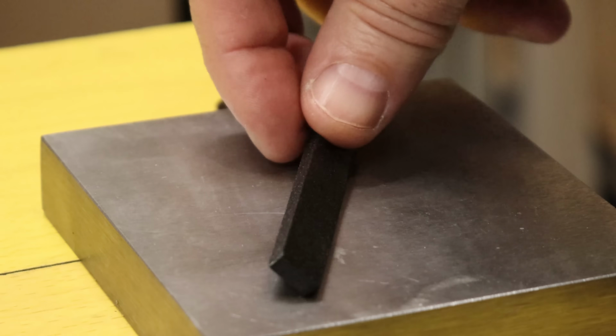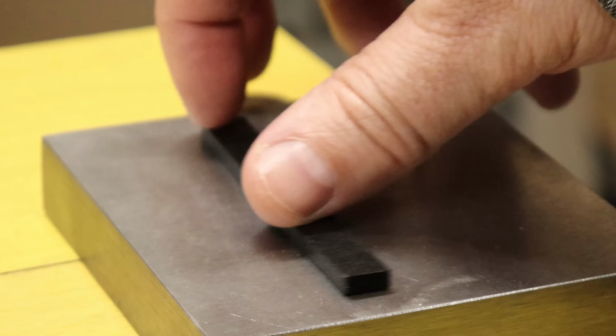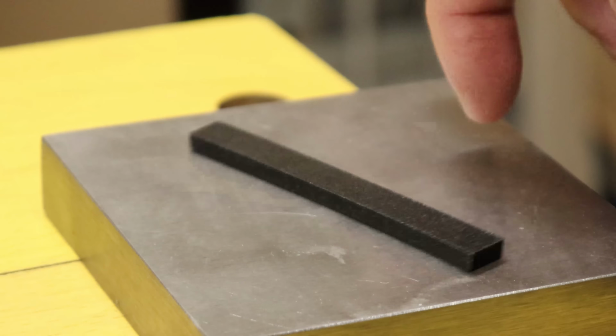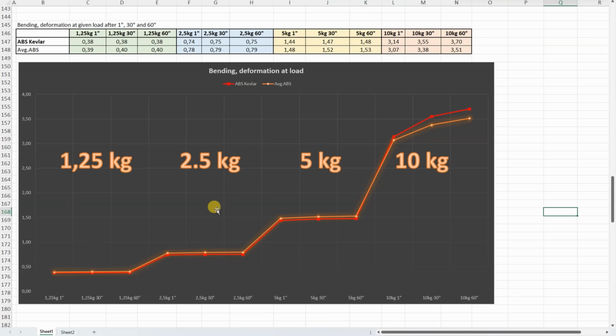And after this test, there is some minimal permanent deformation. The deformation is very similar until 5 kilograms. Now under 10 kilograms we can see some additional deformation on ABS Kevlar during that 1 minute compared to the average ABS, which is not really typical for fiber reinforced materials.